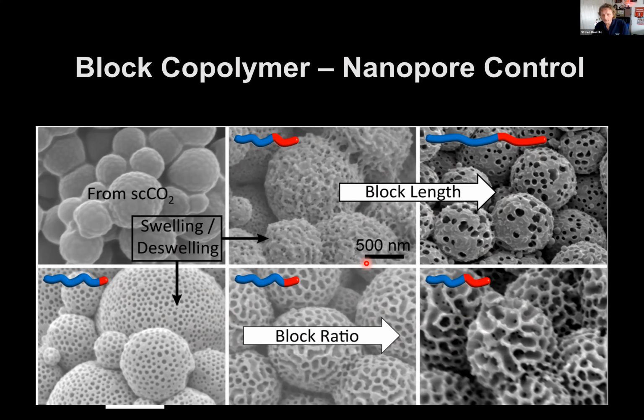One of the things we did here was we've got a very good electron microscopy suite in Nottingham, and started working very closely with the electron microscopists, and they showed us some really fancy techniques. I'd never heard of slice and tilt, but it's a sort of tomography that you can carry out in TEM, transmission electron microscopy. I'm going to show you a little movie that we built up of two of these particles.